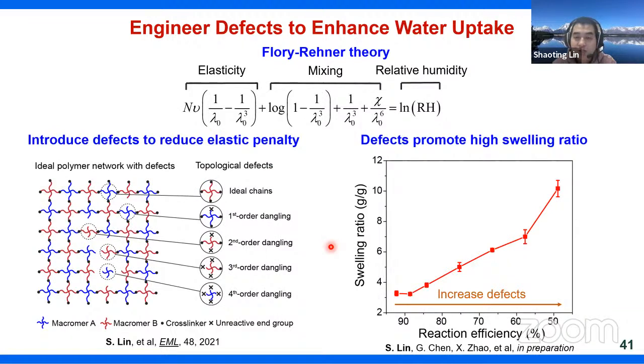So here are some preliminary results. What we found is as we increase these defects, the swelling ratio increased dramatically. This gives us the confidence that it will be possible to engineer defects to further enhance this water uptake or sorption capacity in hydrogel systems.